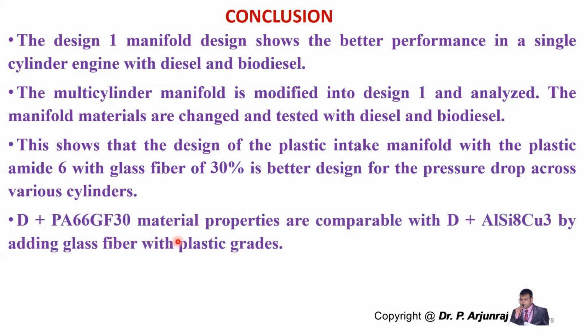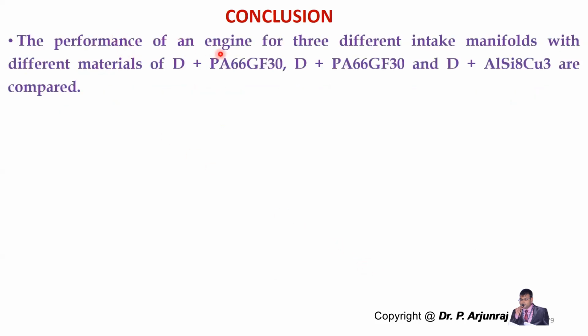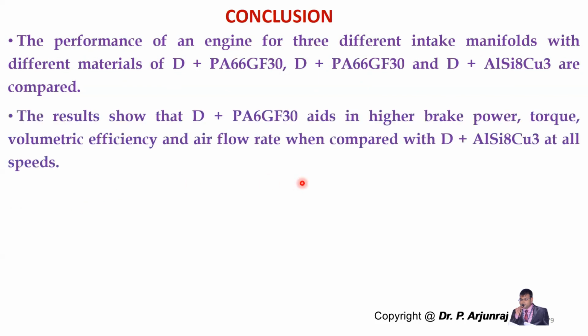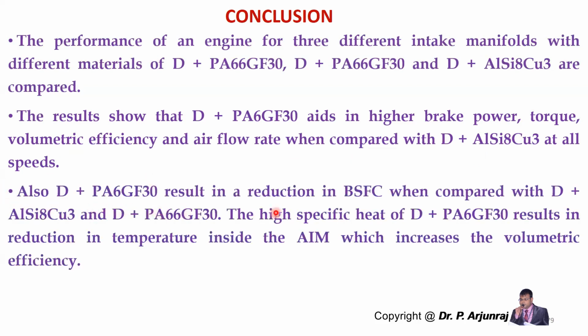Diesel plus PA66 glass fiber 30 material properties are comparable with diesel plus aluminum silicon copper, by adding glass fiber to plastic grades. And the performance of an engine with three different intake manifolds of different materials, D plus PA66 glass fiber 30, D plus PA6 glass fiber 30, and D plus aluminum silicon copper, are compared. The result shows that diesel plus PA6 has better brake power, high torque, high volumetric efficiency, and airflow rate when compared to diesel plus aluminum at all speeds. Also, D plus PA6 with glass fiber 30 results in a reduction in BSFC when compared to D plus aluminum silicon copper and D plus PA66 glass fiber 30.